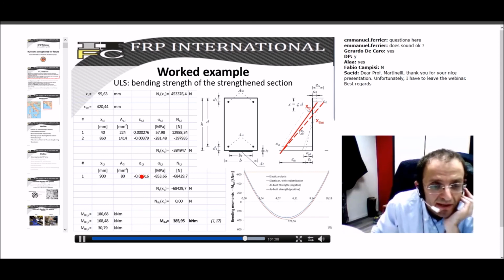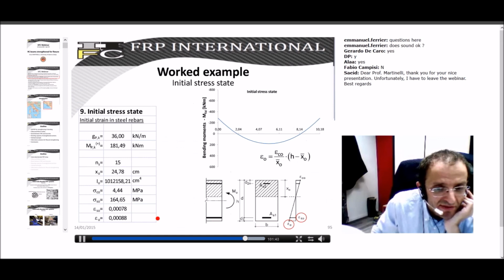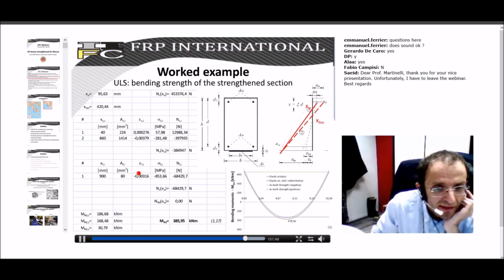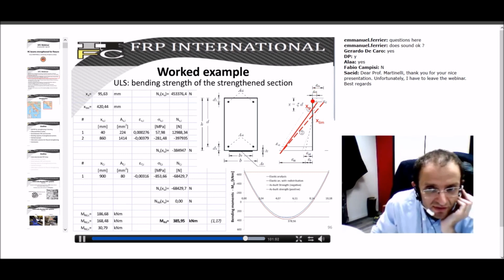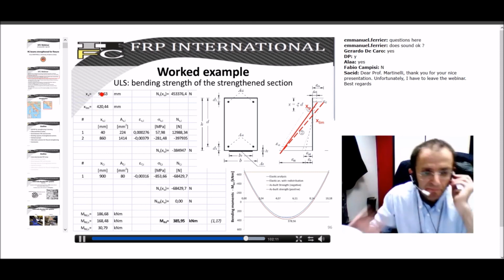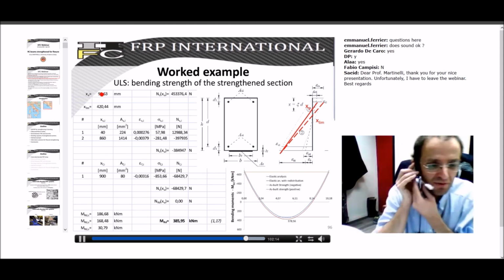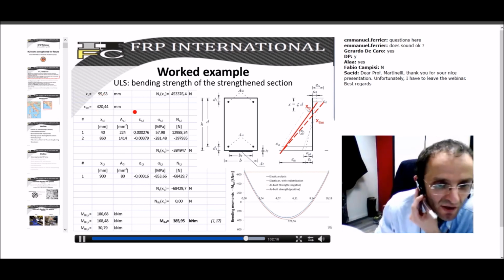How have we evaluated this? We evaluated this by internal compatibility and then by subtracting epsilon zero. You know? So we have evaluated the epsilon Fy by considering the maximum epsilon u, doing the similitude in this triangle, and then by subtracting epsilon zero. Once you evaluate this, we have multiplied it by the Young modulus and then by the area. We have obtained this and this. If you sum this plus this plus this, you get 0. Of course, this was a solution obtained via a numerical procedure which can easily be implemented in Excel.